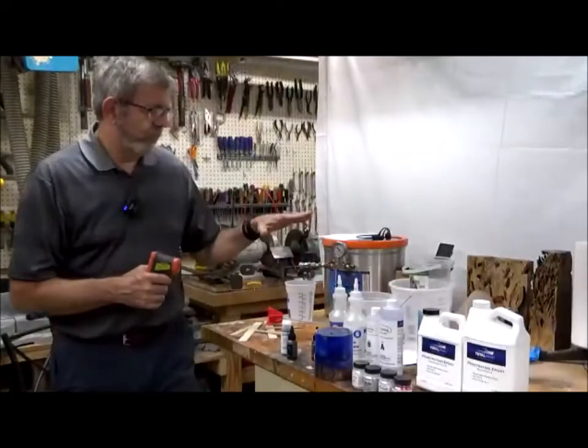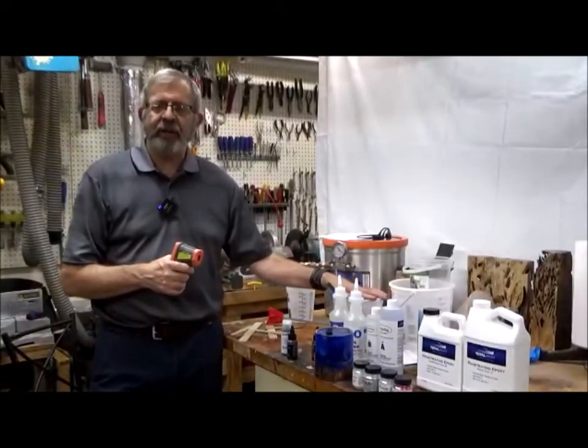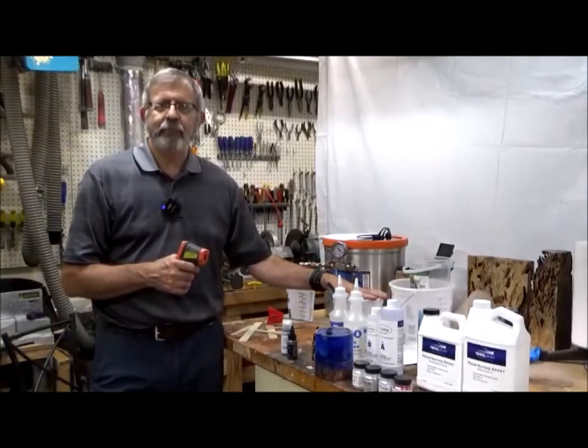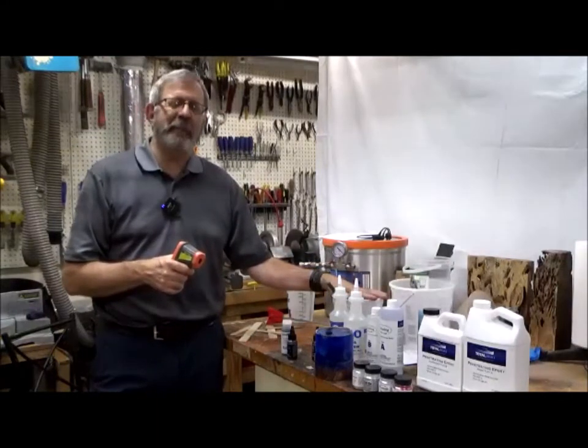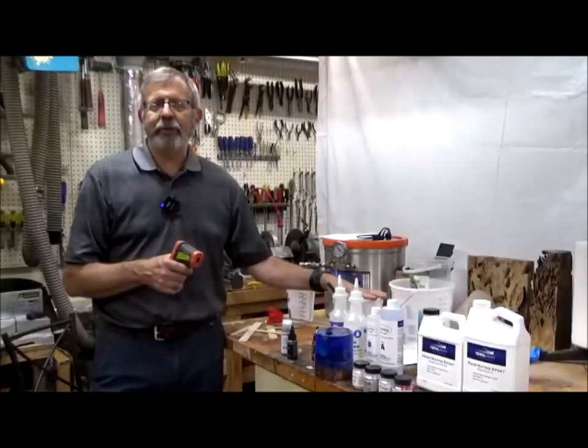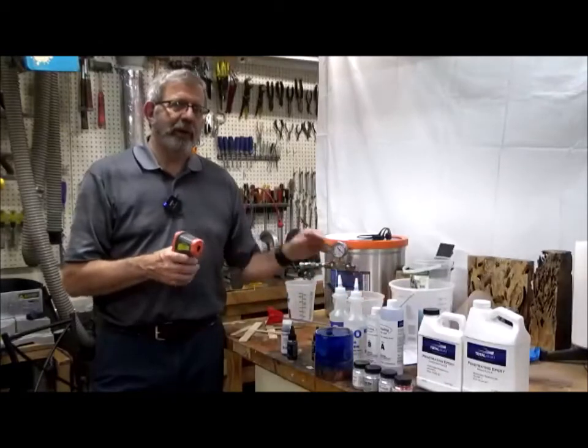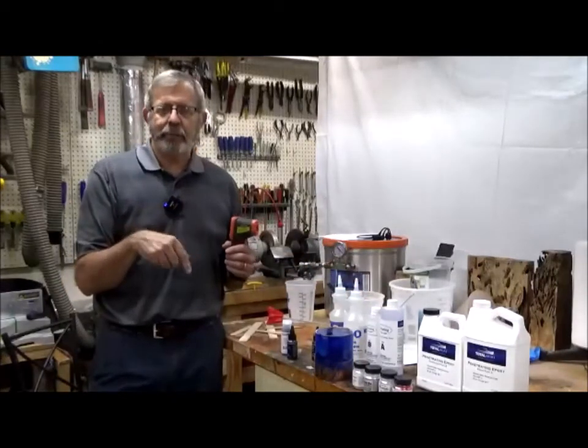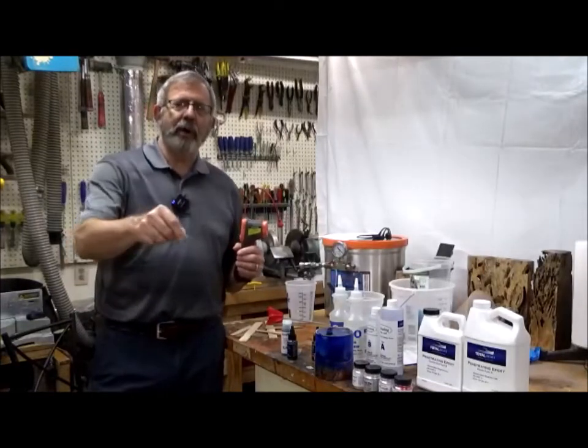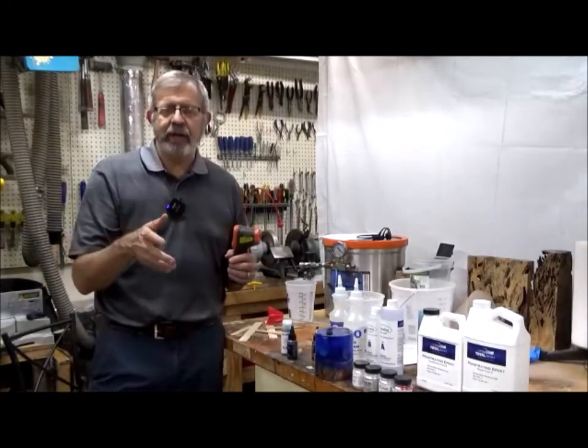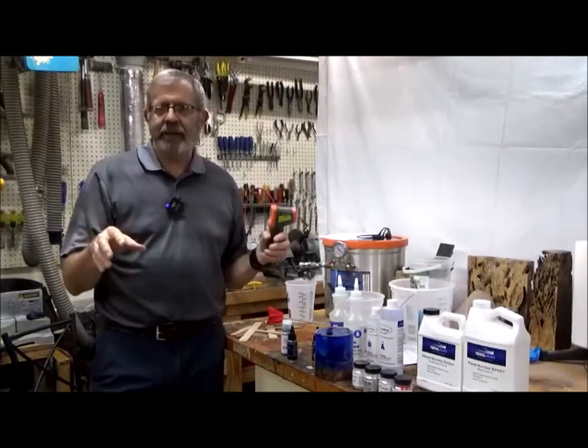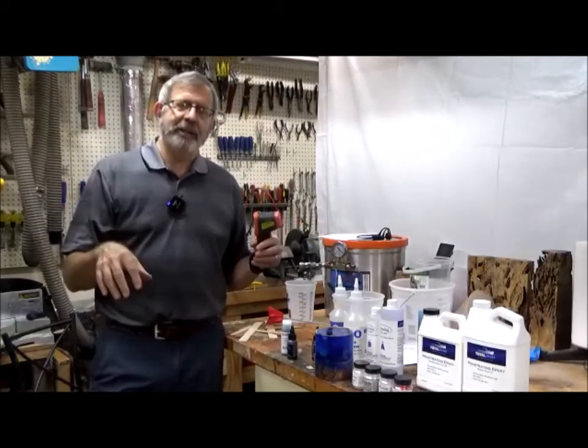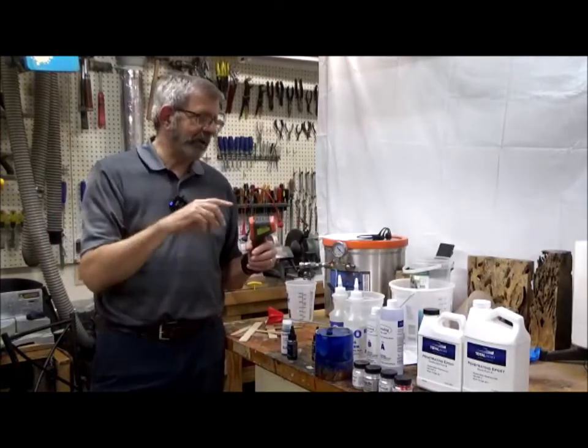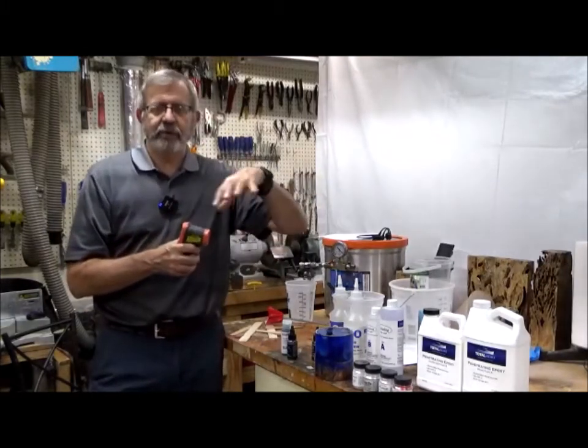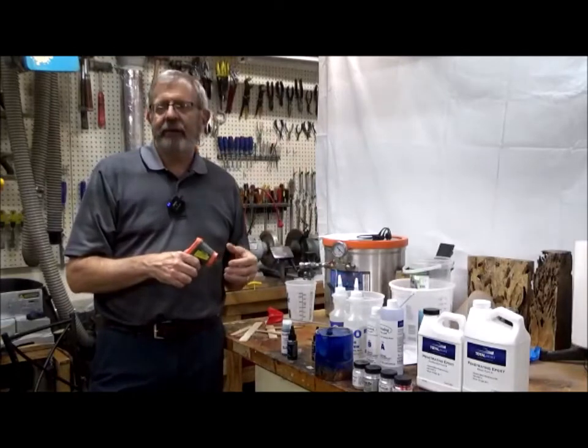I've learned from experience that when I have this material in the mold and it reaches 95 degrees, it's about to flash. I have about a minute to get this done, but it also gets more viscous at that point. So I'll take what's in the second cup that has a pearl powder mixed in with it, and pour it over the mold and maybe stir it in a little bit, maybe not, and then button it up under pressure. Again, I have about a minute to do that pouring, get the lid on the pressure pot and get it under pressure. I'll show you some pictures of some finished pieces that have a very swirly pearl effect in them. That's how I achieve that.